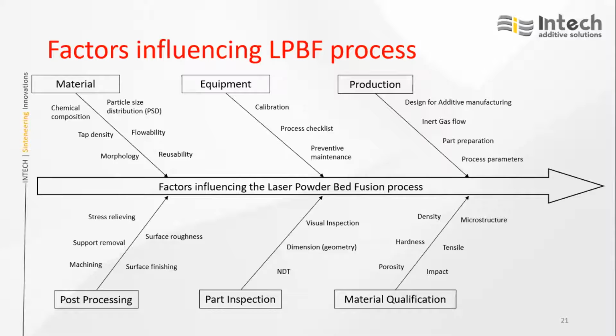When it comes to material, in this process the input material is powder. So at the powder stage, all these major elements like chemical composition, tap density, morphology, flowability, particle size distribution, and the number of times the powder has been used need to be checked.